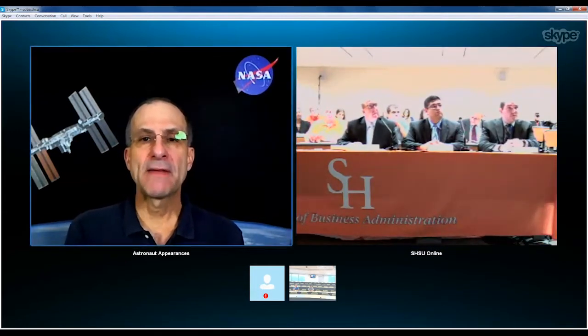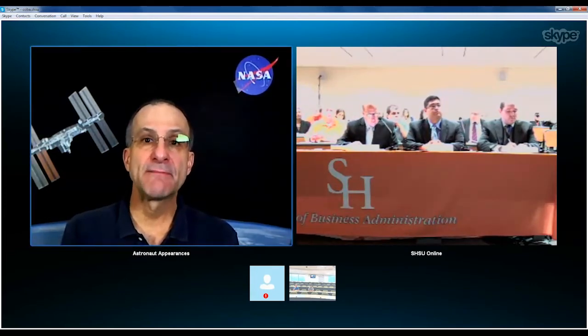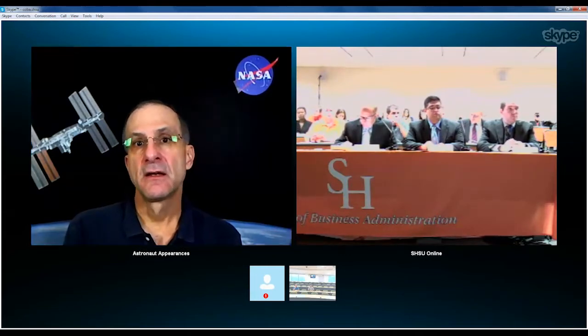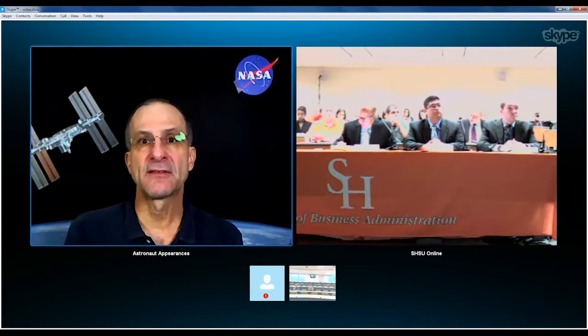Yeah, the borate-based glasses lower the melting point, and they also help clean the surface that they're bonding to, and it acts as a wetting agent. So silica by itself, if you were to put powdered silicon dioxide in the silicone oil, that has such a high melting point, and it doesn't tend to wet a lot of material. So if you mix borate-based glasses with it, then upon heating it'll make a material that has a much lower melting point, and it free flows easier, and then it will lower the wetting angle so that it'll kind of creep across the surface, and that's what I wanted in terms of using this as a compound to glue the patch on.